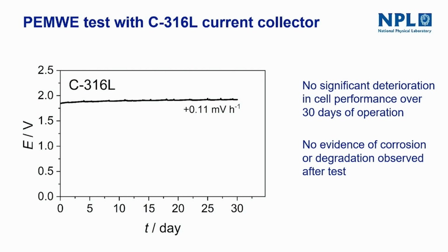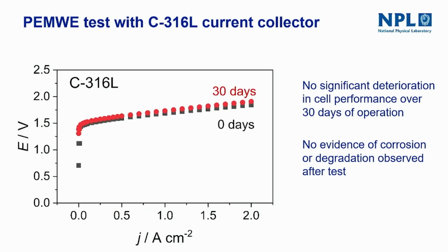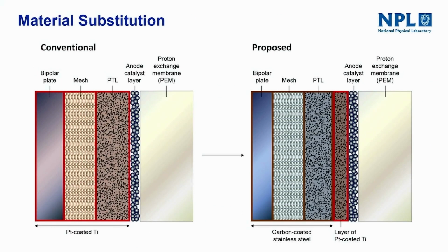So you have to have some kind of spacer layer there to make sure that doesn't happen. And again, looking at the polarization curves before and after confirmed that there was very little degradation during the test. So this is our idea. This is what the situation is at the moment.